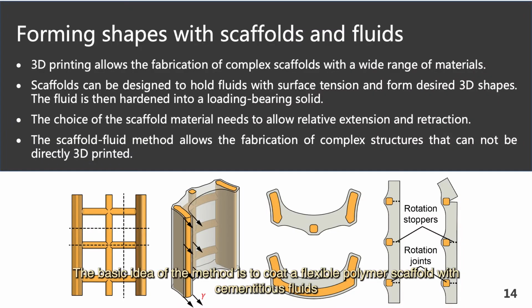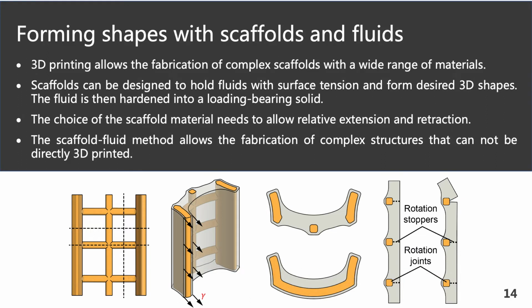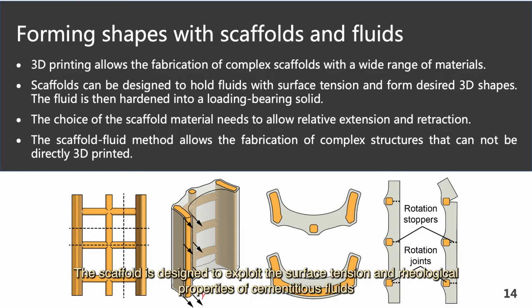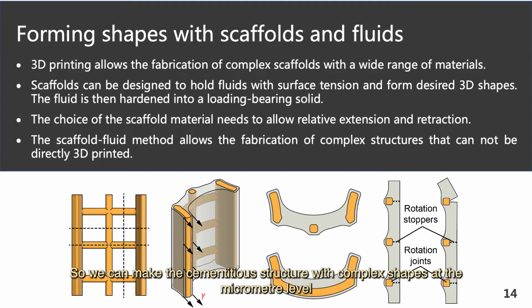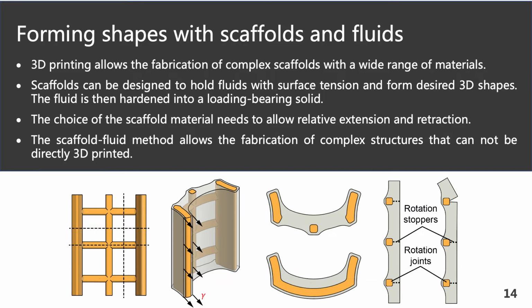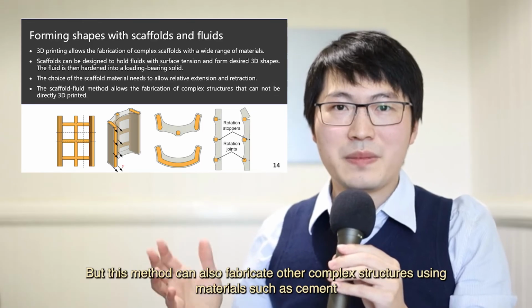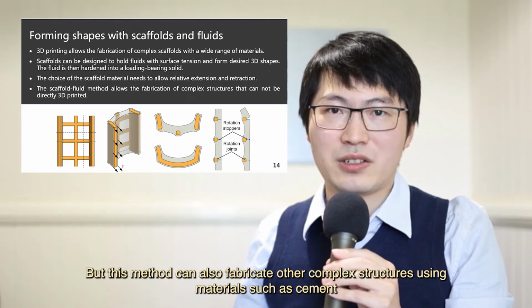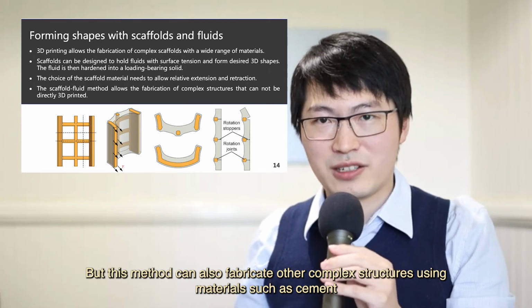The basic idea of the method is to coat a flexible polymer scaffold with cementitious fluids. The scaffold is designed to exploit the surface tension and rheological properties of that cementitious fluid, so we can make the cementitious structure with complex shapes at micrometer level. In this case, we used this method to fabricate the segments. But this method can also fabricate other complex structures using materials such as cement.